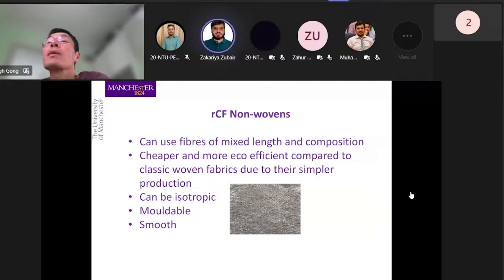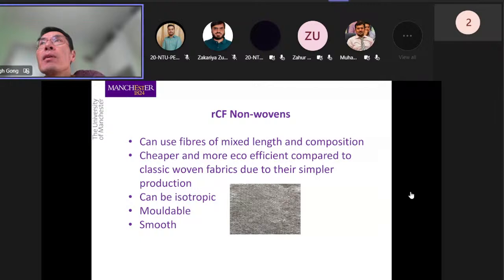Okay. As I mentioned earlier, most of the recycled carbon fibers tend to be used in nonwovens because nonwovens are very flexible. We can use all sorts of fibers in terms of length and composition. We can mix them. It's not very fussy in terms of what the fiber property should be. So nonwovens are used very widely to produce products from all sorts of different types of recycled carbon fibers, including recycled fibers from clothing.